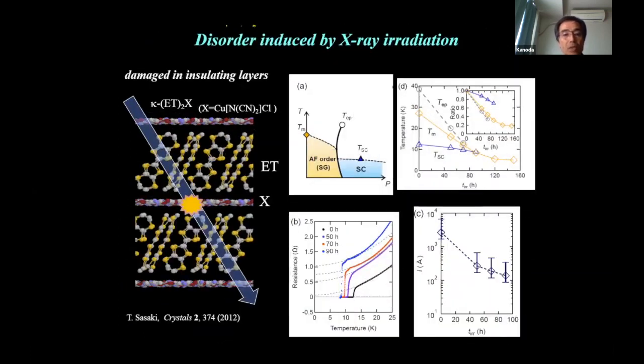So we did X-ray experiments, but in this case, X-ray induces disorder in the materials. And this is a phase diagram of these materials, and we irradiate X-ray to them, and this is the irradiation time. So this critical endpoint is decreasing sharply against the irradiation time. And then magnetic ordering is also decreasing, and superconducting temperature is also decreasing. This is the effect of the disorder. But interestingly, the disorder is not so strong. It's a very, very weak disorder.